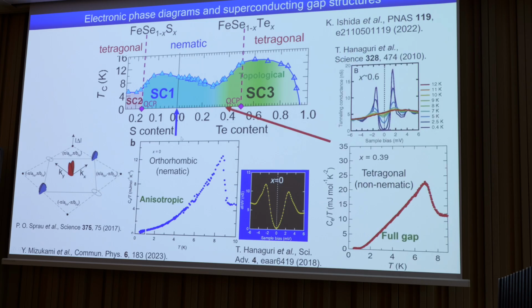However, if you go into the SC3 side, you start to see a flattening behavior in the C over T at low temperatures, indicating that the gap changes to a fully gapped state. You can also look at the tunneling data, which shows a U shape, or you can find a flat portion at low bias. So clearly SC1 and SC3 have different gap structures.